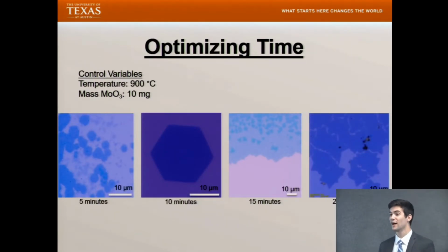After temperature, I optimized the time of growth. So I found that growing for under 10 minutes led to domains with very poor crystalline structure. You can see this from the 5-minute image. They're more amorphous than crystalline. However, if I grew for more than 10 minutes, the domains would grow too large, forming this continuous film that you can see here. And this film just had too many layers and too many grain boundaries for electronic applications. So I was able to determine an optimal duration of 10 minutes.